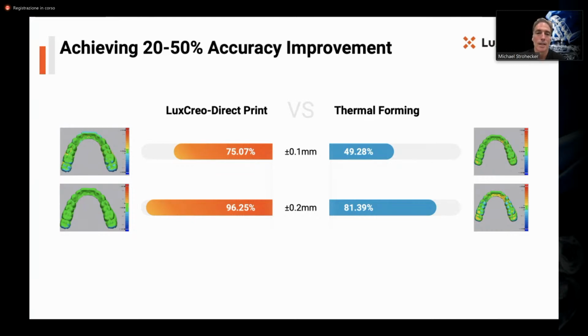They go with a 100 or even 170 micron layer thickness. The printers themselves don't have much uniformity across the build area, which affects accuracy. The resins themselves have high shrinkage or have other limitations in maintaining accuracy. So there's a lot of inaccuracy in the ortho world for models. So that's where you start from.